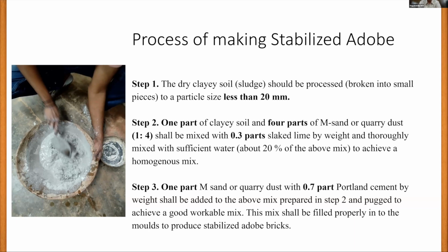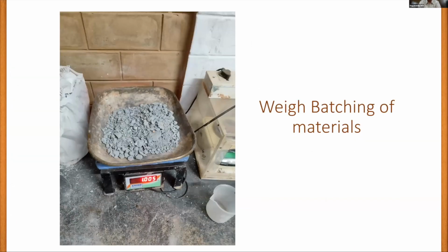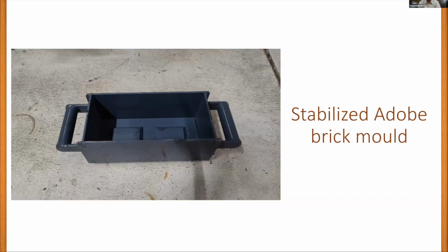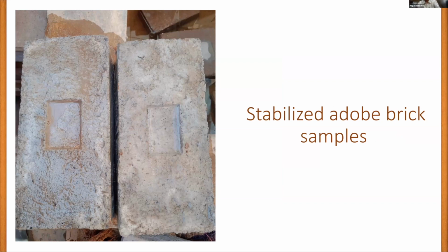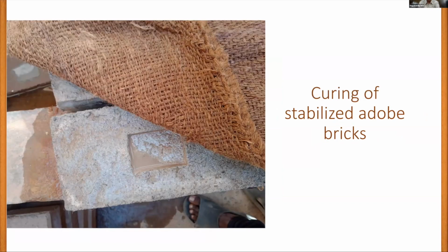That's when we use a mold. This is just to show we need to weigh batch it. Then the stabilized adobe mold, you can make of different sizes. You can manufacture the mold with a bottom plate. This mix, what is prepared, should be filled properly into it so that the air gaps are not there. This is the stabilized adobe brick sample, which was made using that mold. The size of this is 9 inches by 4 1/4 by 3.5 inches.